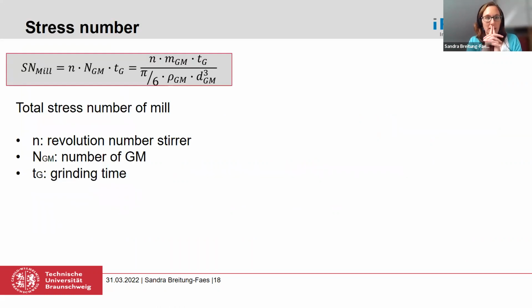And therefore I thought, okay, in general, I would need 2 different grinding or stress numbers. On the one hand side, I have a stress number of the mill. This is the number of grinding media contacts which is delivered by the mill during my grinding time. And so you can see here the revolution number of the stirrer. Instead of using the grinding media contacts, which we for sure don't know, we introduced here the number of the grinding media, and we have the grinding time. You can express the number of the grinding media by their mass and their size and density, for example, but also by their filling ratio.